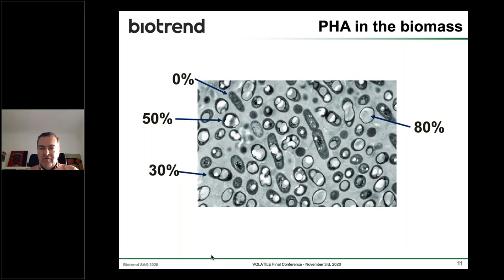And so it's a challenge in a way, because when you try to extract the PHA, you need to first digest the outer shell of the cellular content in order to release the biomass. And the conditions which are optimal to extract the PHA from a cell which has 80% of polymer are, of course, not the same as the requirements and conditions to extract the polyhydroxyalkanoates from a cell which only has 30% of polymer. Since you're using a mix, the processes need to be tuned in order to release and purify the PHA to a certain extent in order to reduce the levels of impurity, but also not to try to digest the PHA itself.